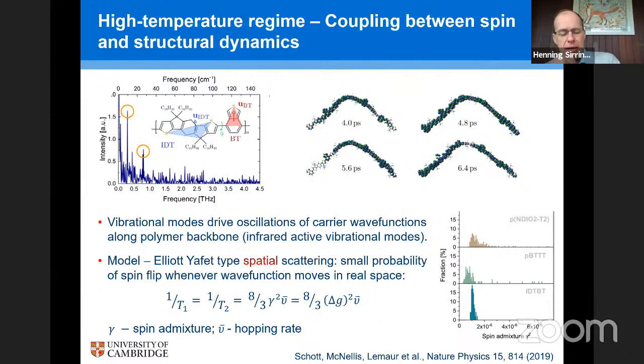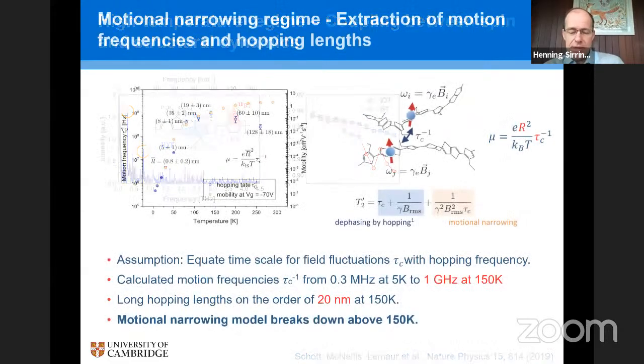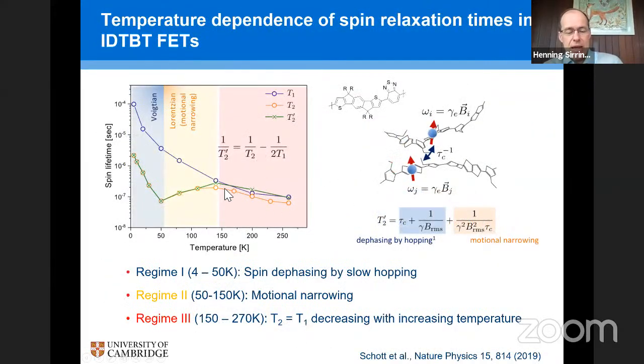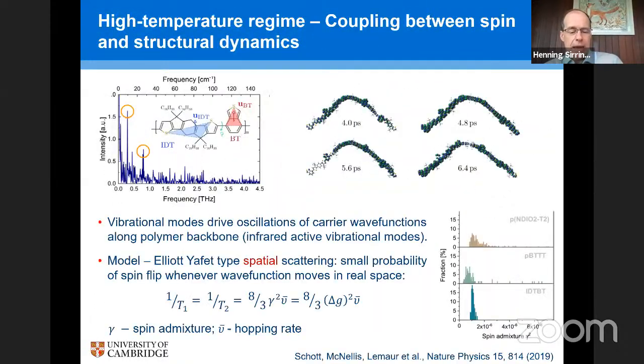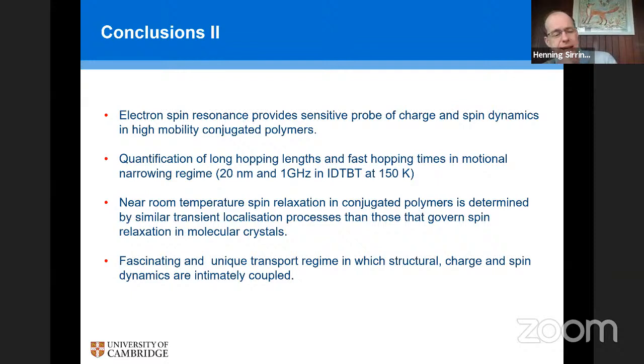And together with Eric McNellis and Jairo Sinova's group, we've developed a reasonably quantitative model for this mechanism that's in good agreement with the spin relaxation times that we see in this high temperature regime here. It explains why the spin relaxation time decreases with increasing temperature in this regime as the molecular vibrations become more and more important. So this is a very interesting observation, because it builds a link between the molecular systems that I talked about in the beginning and the polymeric systems.